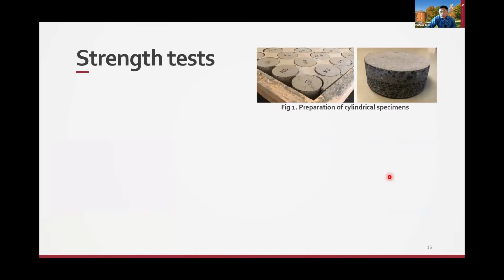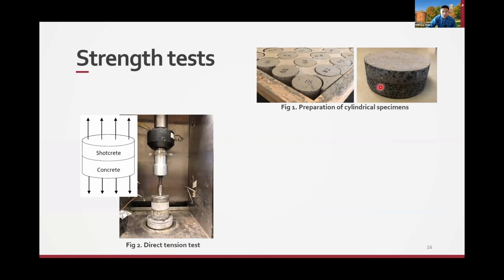Then after you do the surface preparation, you blow off the dust, and then you shoot the shotcrete vertically onto the panel. And then you bring it back to the lab, and you use the water jet to cut the sample this way. So you can drill it using the coring method. The problem is during the drilling, you're applying torque and shear, which possibly can damage the bond. Sometimes the bond can be really weak. So then you get this sample, and you can do the tension test, like what you have seen here, just pulling the sample. There will possibly be bond failure between the shotcrete and the concrete substrate.